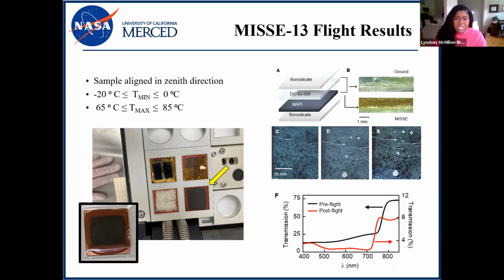So from this, we can acknowledge that we don't see any visible new spots that were created due to space flight. And panel F is transmission data from the MISSE flight sample, and black is the as-made device and red is post-flight. And there's a relative drop of about 30 to 40% transmission intensity broadband. And this reduction is expected actually because our substrate was not selected for optimal radiation tolerance. So we opted for borosilicate substrate because it's more easily sourced, and it's favorable for our deposition protocols of the MAPI ink. However, we would want to use a space qualified glass, something like a ceria-doped borosilicate in future flights, and that glass would be less likely to darken.